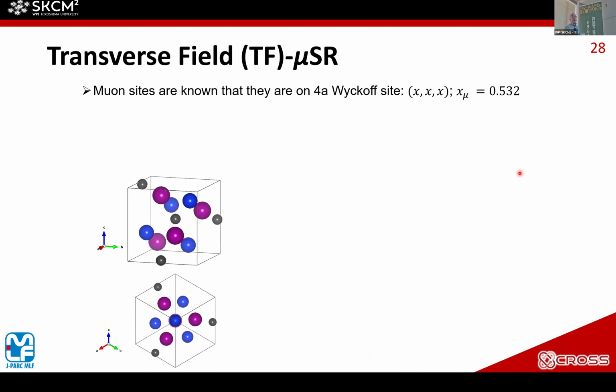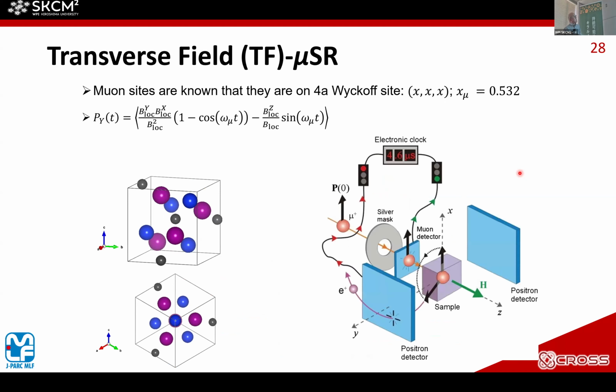Manganese silicide is a very old material, so there are many muSR papers on manganese silicide. So we know where the muons stop in manganese silicide. There are 4 muon sites in the unit cell. And then we perform the transverse field experiment, in which the applied field is perpendicular to the initial spin direction.